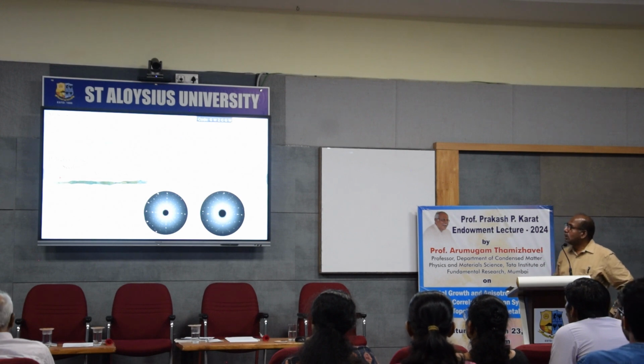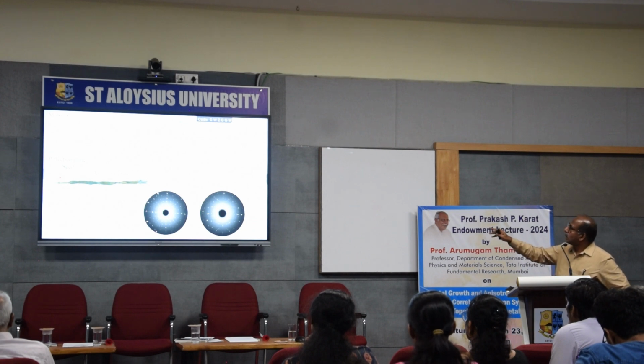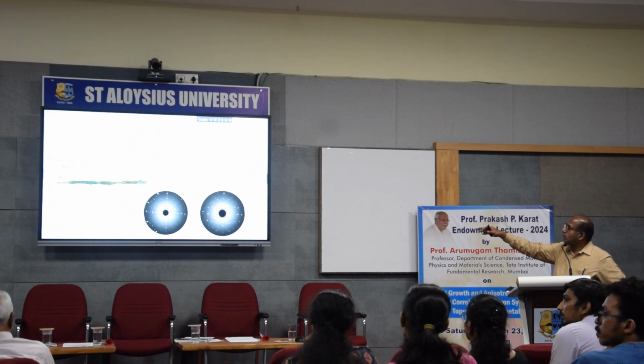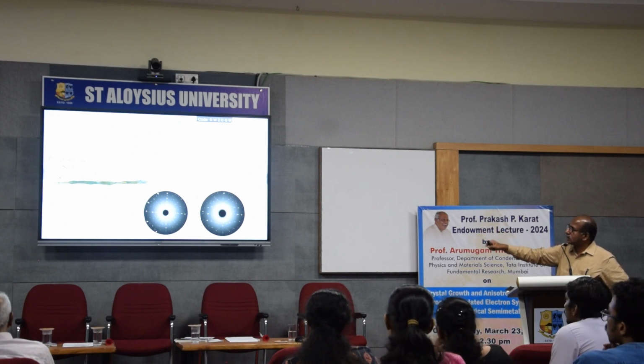And this is one of the recent crystals that we have grown. These form in these semi-metallic systems. Again, you see MoSi2, which melts at around 2080 degrees centigrade, on the right hand side. Again, the same process: we made a polycrystalline sample, cut a seed crystal, inserted the seed crystal and slowly pulled it. And we got a beautiful, textbook-like Laue pattern.